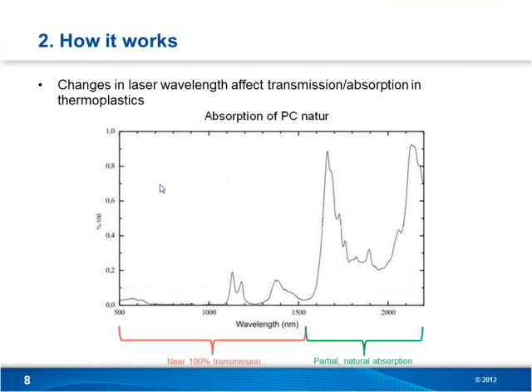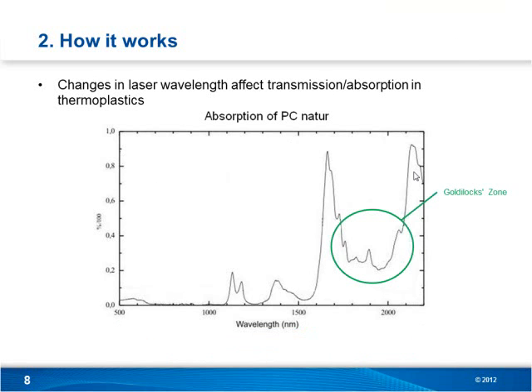So again, the plastic is still in its natural state, but we want to have the ability to absorb some of that laser radiation into the plastic. Once you get up above 1500 nanometers, the laser wavelength starts to react differently to the thermoplastic. What we have is these peaks and then this small valley. But what we're really getting at is between about 1700 and around 2000, we have what I like to refer to as the Goldilocks zone. It's where we can get some of the laser energy to pass through and some of it to absorb.